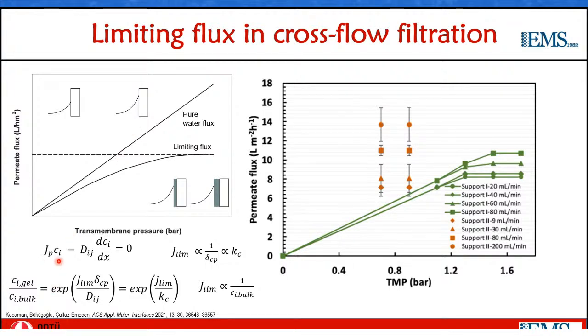So when you consider this mass transfer boundary layer, or the concentration polarization boundary layer, and do a species balance for the rejected species, for 100% rejection, this is what you end up with. So you have the permeate drag term towards the membrane, and you have the back diffusion term away from the membrane. And in the mass transfer boundary layer, these are balanced with one another. And when you suitably rearrange and integrate this expression, you can obtain a relationship between the bulk concentration at one end of the mass transfer boundary layer and the concentration at the membrane wall in relationship to the flux and the diffusion coefficient and the boundary layer thickness.